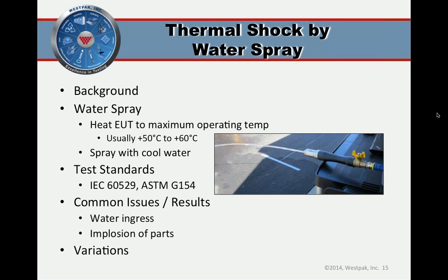The heat capacity of water makes this a very convenient medium for quickly changing the temperature of a product and other components. There was a really neat landmark study done in 1955, just recently declassified. It was done by the Jet Propulsion Laboratory, and it showed the potential for disastrous cracking of impeller blades when a jet turbine engine is subjected to a water spray. It was originally intended to increase the power of the jet engine by inducing some fluid into the compressor section. They found out that the turbine blades didn't like that a bit.